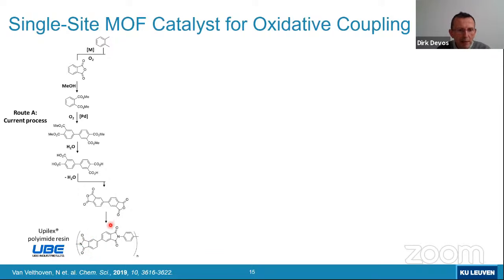And actually, if they make it, they need this type of bisphthalic anhydride type of molecule that they produce via quite a detour. If you look at how they do this, they will first oxidize the orthoxylene to phthalic anhydride and convert that to the double ester. That double ester can, with homogeneous catalysis, be coupled to this biaryl molecule, which then needs to be deprotected again and so on, and be converted to the double anhydride. And then you can think about making your polyimide.